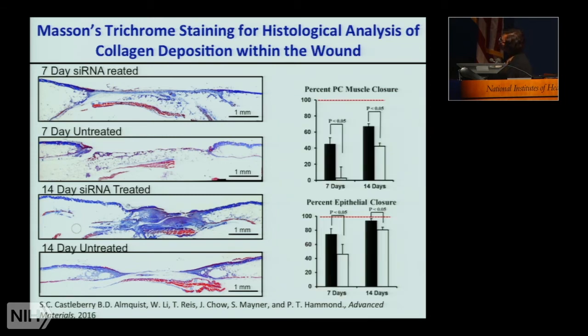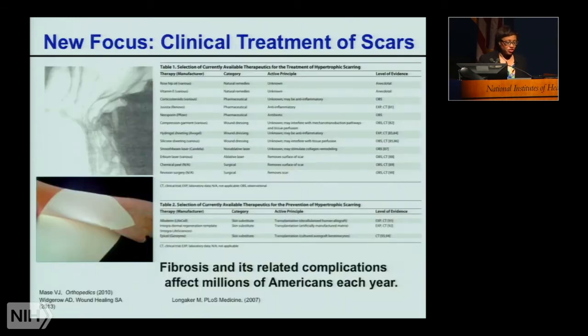And we also see very real contrast in the rate of wound closure in these systems. Here we have a 7-day and 14-day, and the dark bar is our treated sample. And we also see an improvement in the percent epithelial closure in these animals. This is really just the beginning. There is more than one gene involved, of course, in these kinds of wound healing processes. And what we're interested in now is combining targets with siRNA and using growth factors in our combination systems to be able to address this more effectively by replicating the wound healing process.